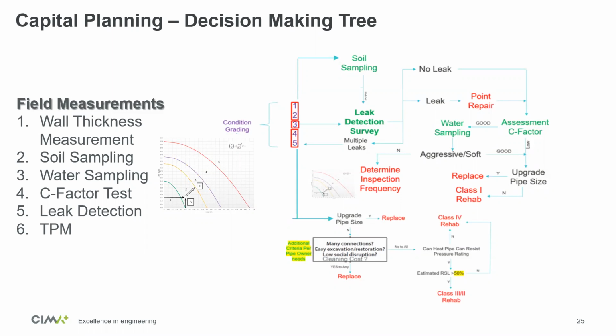What does the C-factor provide us? It provides us the internal condition of the pipe. If the C-factor is low, it means that it has a lot of tuberculation inside the pipe. Then we ask ourselves, do we need to upgrade that size? If the answer is no, then we go with a class 1 rehab. And what is class 1 rehab? It is basically relining, an internal coating inside the pipe to make the pipe smoother and to improve the hydraulic performance. If the pipe needs to be upgraded in size, then we will replace the pipe because we already know that we need to upgrade that pipe.